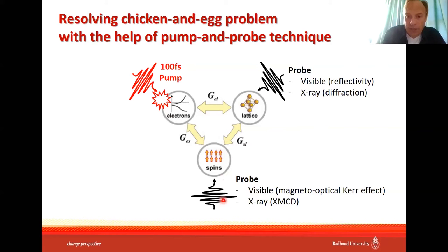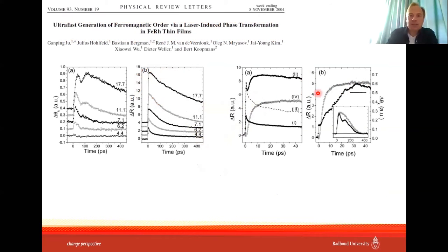and then we can follow what's going on with iron and rhodium, measuring either magneto-optical effects, also optically in the visible spectral range, measuring the magneto-optical Kerr effect, or using magnetic circular dichroism in the X-ray spectral range, we can measure the so-called XMCD. And we can also be sensitive to the lattice changes by measuring reflectivity. Simple reflectivity must be sensitive to the lattice expansion. And also X-ray diffraction can be applied in this case. And as I said, the first experiments were done quite some time ago, in 2004. People applied the magneto-optical Kerr effect to measure the dynamics of the phase transition in this material.